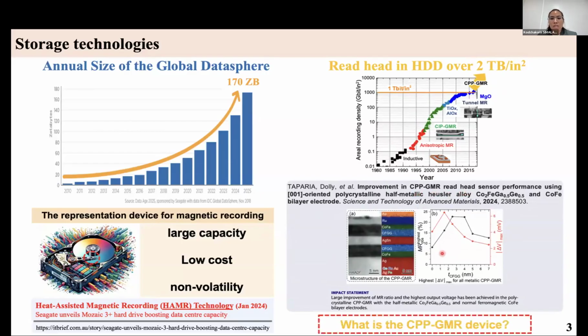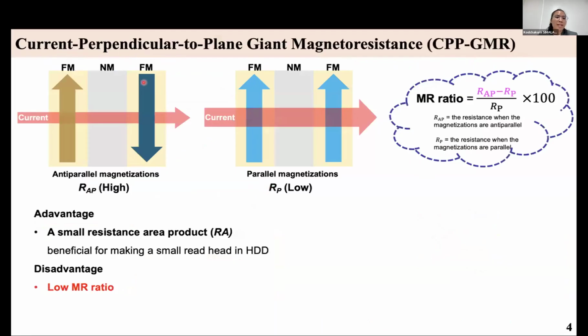So what is the CPP-GMR device? CPP-GMR stands for current perpendicular to plane giant magnetoresistance. This device is a type of magnetic sensor that relies on the giant magnetoresistance effect, which is a phenomenon where the electrical resistance changes in an applied magnetic field. The device consists of two ferromagnetic layers separated by a non-magnetic spacer, with the electrical current flowing perpendicularly to the plane of the device structure. When the magnetization directions in the ferromagnetic layers are anti-parallel, the total resistance in this state is high, otherwise it is low. The difference in resistance between these two states we know as the magnetoresistance ratio or MR ratio, which can be described by this equation.